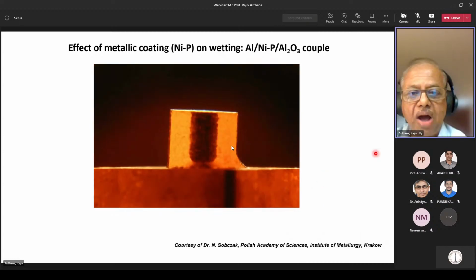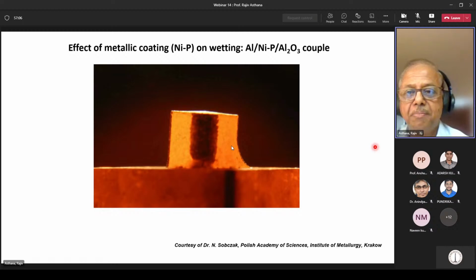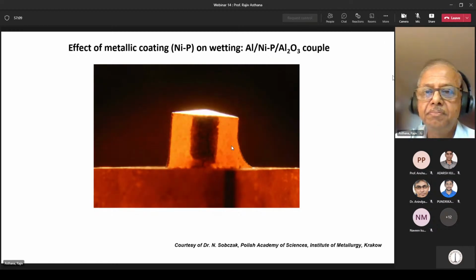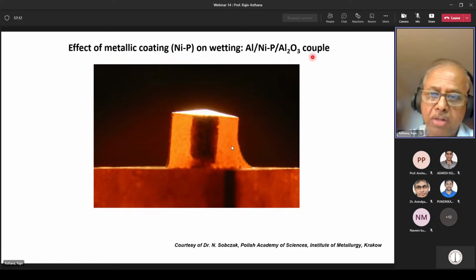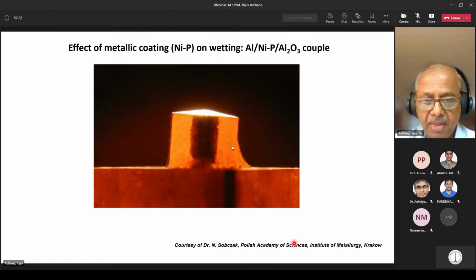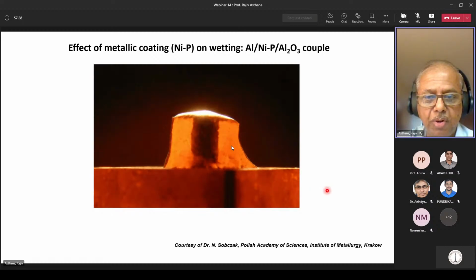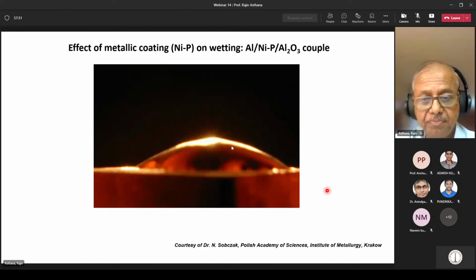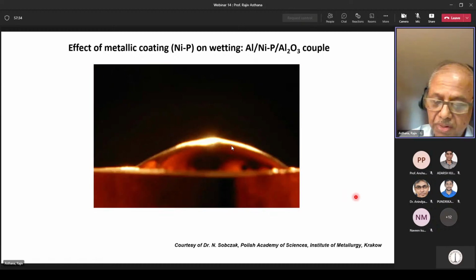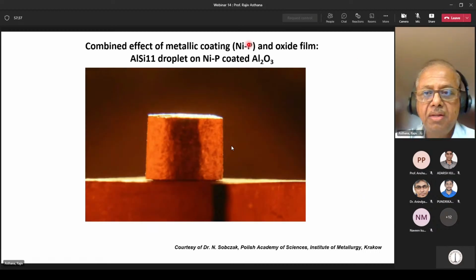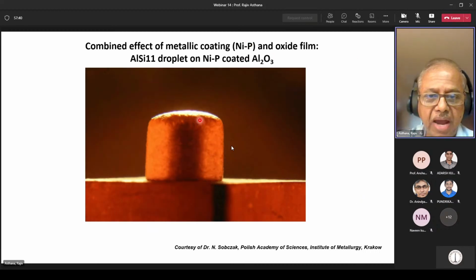So here is an example of how we study wettability in some systems. We are looking at aluminum droplets spreading on aluminum oxide substrate with nickel phosphorus coating on it. So these were the tests done in Poland. And you can see that the liquid melts and begins to spread on the surface here. Now, if you did the same kind of experiment in an environment where oxide film forms on the droplet, the oxide prevents spreading of the liquid on the surface. And you can see this here.